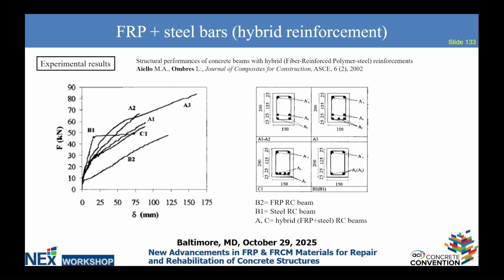And the idea is that taking those tests, they want to compile a large database and then verify and possibly improve the formulations, especially for assessing the cracking stiffness and for predicting the deflections and serviceability. Now, this was a work done by Luciano more than 20 years ago, where B1 is a typical steel beam and B2 is only GFRP, and you can see that the combination of the FRP with steel can improve the overall performance.